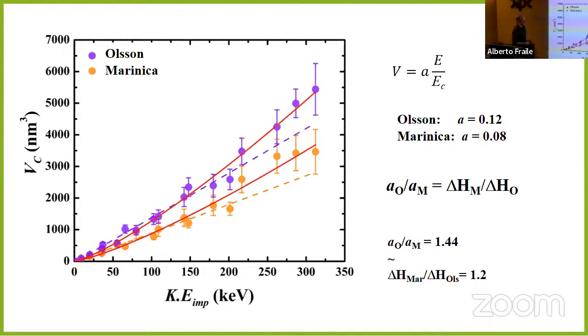And it looks like the ratio between these two slopes is about the ratio between the two latent heats of melting of the two potentials. So with this potential, the latent heat of melting is lower. So you need less energy to melt the tungsten according to this potential. So you have a bigger crater with the same kinetic energy. And it's not exactly like that, but it seems that it's an important contribution.